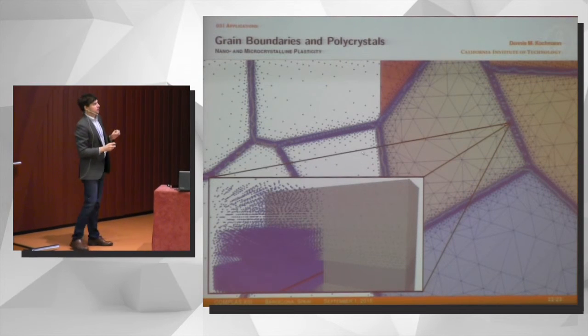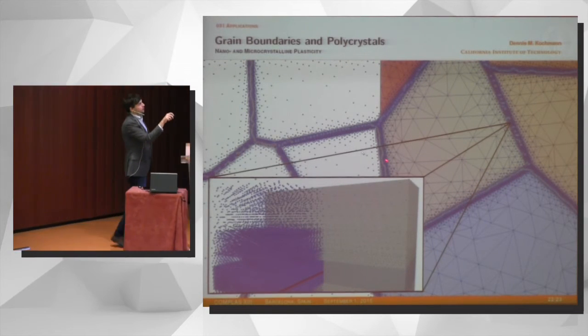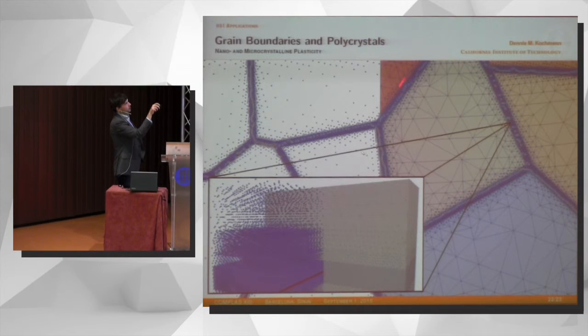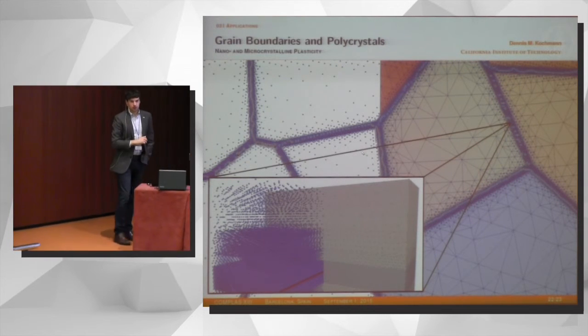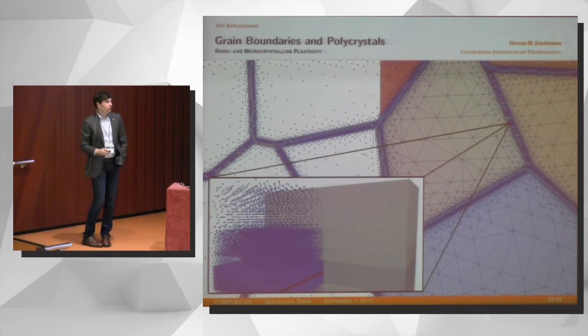In this case, there's not much of dislocation-mediated plasticity. And so you could consider a scenario where you have full atomistics near the grain boundary, you coarsen dramatically on the inside to speed up your calculations.